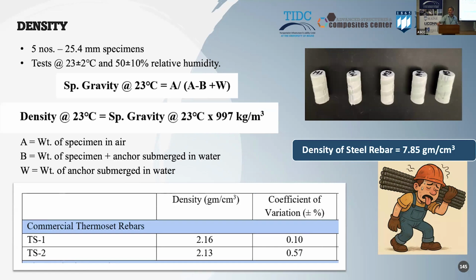Next one. Then we look at density. And Rohan put that picture there. It's quite visible, trying to emphasize the density of steel at about 7.85 grams per centimeter cube and how these materials compare to that. So we measure density based on specific gravity. We are reporting here the values. They're about 2.1 for both thermoset bars that were studied. We also reported always, you will see in the tables, coefficient of variations. They are very small, meaning these products have repeatable properties. And now we can look at the ratio with the steel bar, okay? And we see the advantage in terms of weight.